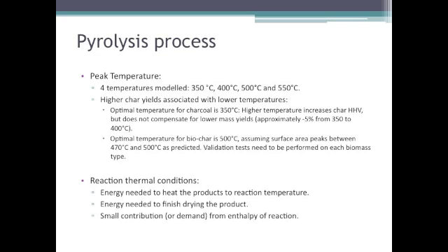And basically what happens is that the total yield of char is higher at lower temperatures, but there's more volatiles in it, which means the fixed carbon content is lower. And so that may be something interesting to mention in your dissertation, that you might want to go to a higher temperature because you'll actually have more or the same amount of stable char.